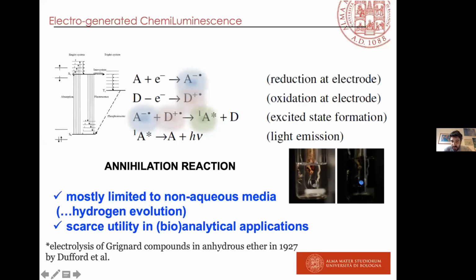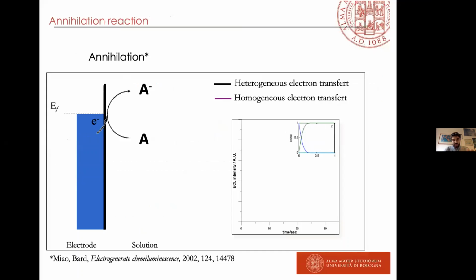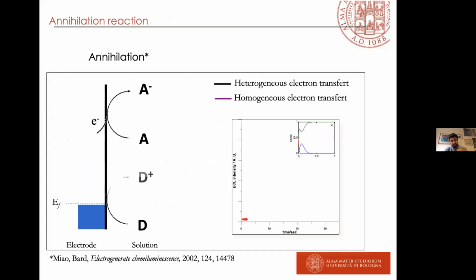Here you can see this nice blue color emitting in acetonitrile. In fact, this mechanism was observed, but this is another story, very early in 1927 by Dufford, who was doing electrolysis in an aprotic solvent, and he observed blue emission in the middle of the two electrodes during the electrolysis. So in annihilation, switching the potential, you go to negative potential and generate the radical, then to the opposite potential, the oxidation potential, and generate the radical again. Both are in the diffusion layer. Here I schematized the diffusion layer. Both are generated at the same electrode, and the two concentration profiles overlap, and you can generate the excited state that afterwards emits and generates light. So a spike of light.